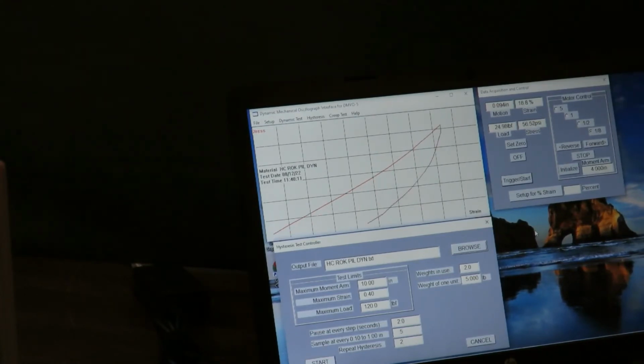It is also important to know about this behavior as something called Mullins effect, meaning if the component keeps experiencing repeated stresses, it softens up. How does it soften up? It softens up because agglomerates start breaking up, forming smaller agglomerates, and therefore voids are lost, so it becomes more dense. But on the other hand, the cross-link structure, double bonds of carbon-carbon bonds are breaking up. As they do, the material softens up.